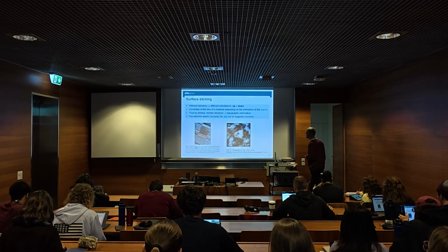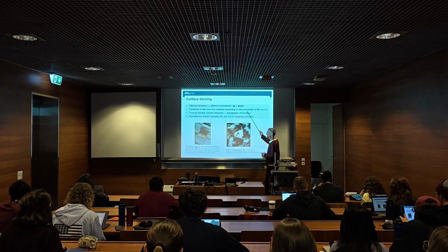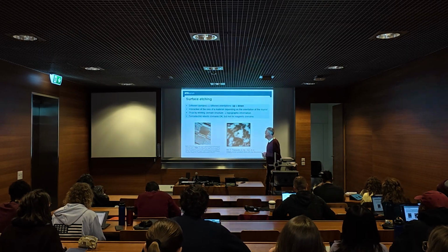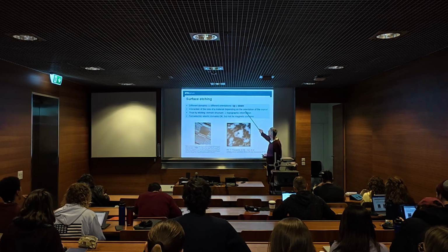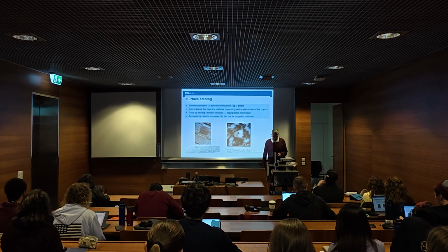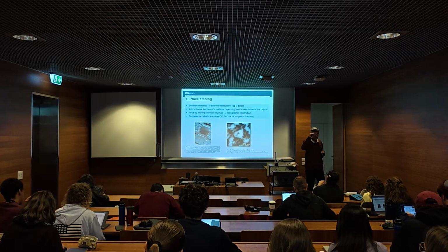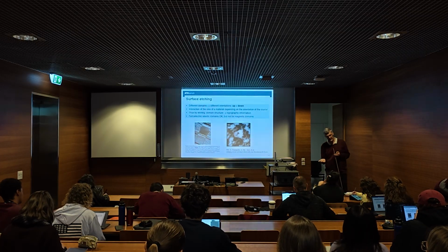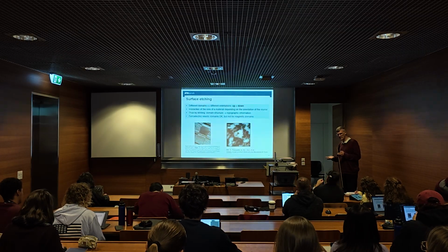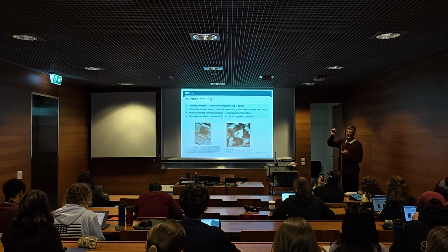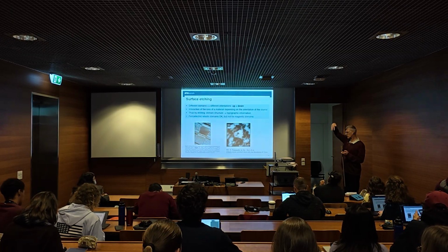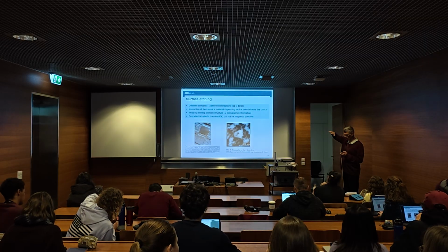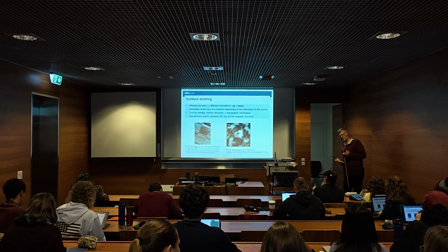So here the idea is that, especially in ferroelectrics, different domains have different orientations, polarization up or down, which means the top surface looks different from the bottom. Ions are displaced, maybe up, and that means that at the top surface certain ions are closer to the surface than at the bottom surface.